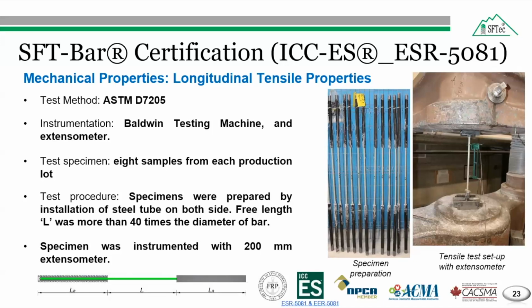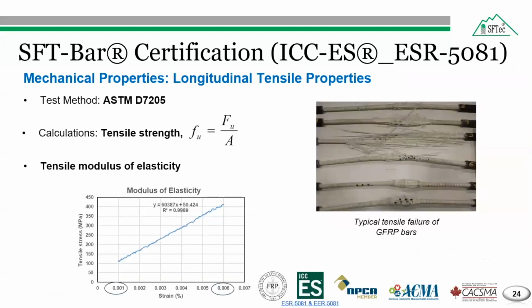The specimen was instrumented with a 200 millimeter extensometer to capture the specimen elongation during the test, and this test was carried out using the Baldwin testing machine. The tensile load was applied until the failure occurred, and the applied load and the bar elongation were electronically recorded using a data acquisition system. And the tensile strength of the FRP bar can be calculated according to the following equation, where Fu is the tensile load in Newton and A is the cross-sectional area of the tested bar in square millimeter.